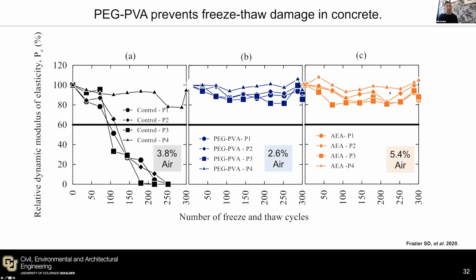looked identical to the air entrained sample, but I'll draw your attention to this 2.6% here. Our molecule, when we use it, does not entrain air. So what we proved in this study was that our molecule was behaving very differently from an air entrainer. It wasn't releasing the pressure that built up from the ice formation and expansion. It was preventing the ice crystals from growing. So this really represented a complete departure from 70 years of air entrainment technology by offering a different route to enhancing the freezing and thawing resistance of concrete.